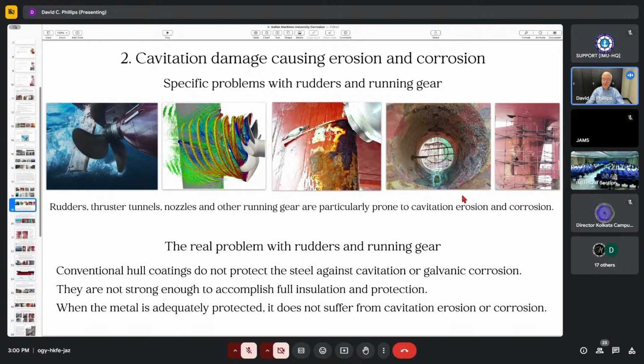Another area that's affected by cavitation is the inside of the thruster tunnel. In here, you have the thruster propeller turning around, creating the same kind of turbulent motion in the fluid. And even though they frequently put a stainless steel belt inside there to protect it, the corrosion occurs anyway. The cavitation will damage the coating, and then the salt water goes to work and you get corrosion. So that's another area that often needs to be repaired.